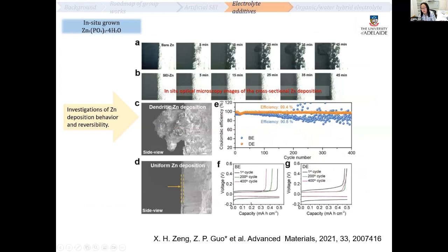zinc deposition. And from in situ optical microscope, we can clearly see without this SEI layer, zinc dendrite grows in 5 minutes. But with this SEI layer, even after 45 minutes of plating and stripping, the surface is still quite smooth. From the cross-section SEM, we can clearly see the difference. So uniform zinc deposition can be achieved with this SEI-coated zinc anode. So due to the reversibility of plating stripping, the efficiency significantly improved.